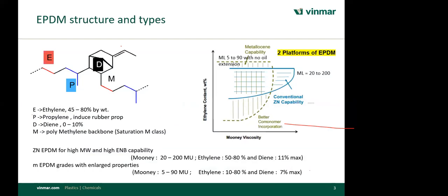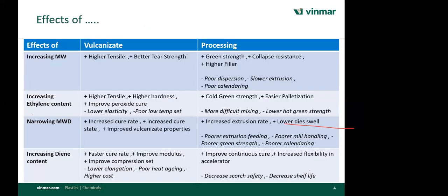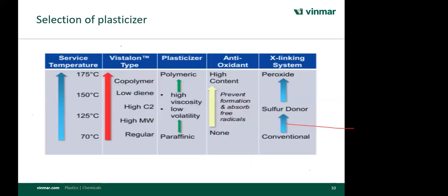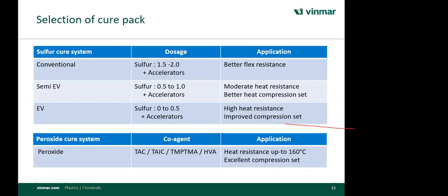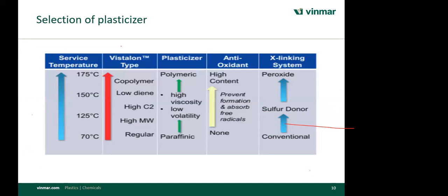Okay. The next is for EPDM, which cure system is better? See, any cure system is better. Again, it depends on your application, and what temperature you want to use your product at. If you want to use it at 70 degrees or 125 degrees, you can go for the conventional curing system. If you want 150 degrees centigrade continuous product use, then you have to select semi-EV or EV system. If you move on to 175 degrees centigrade, where your product is going to sustain for long-term duration in use, then you have to choose the peroxide system.